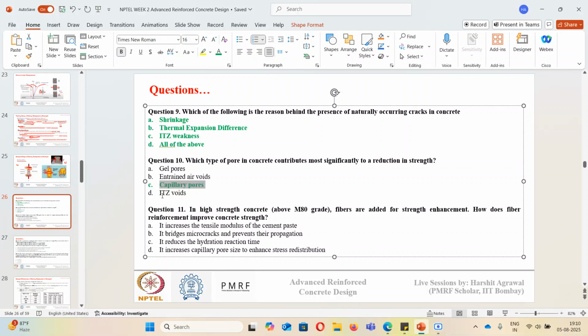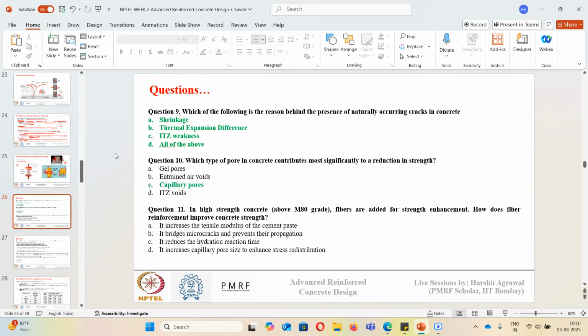ITZ voids and gel pores are minor pores, they are not as big as capillary pores. Air entrained voids are sometimes beneficial, sometimes harmful, but mainly the capillary pores are the ones which significantly reduce the strength. In high strength concrete, fibers are added for strength enhancement.